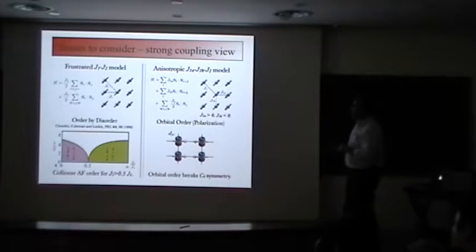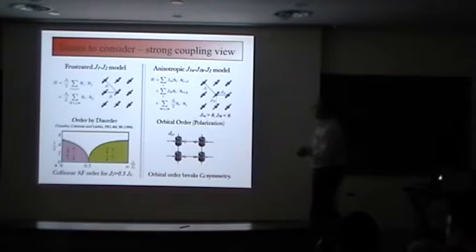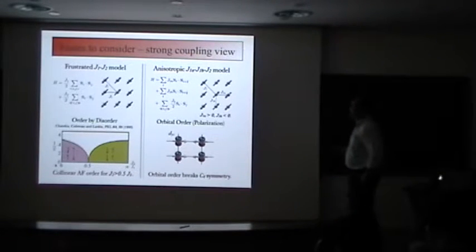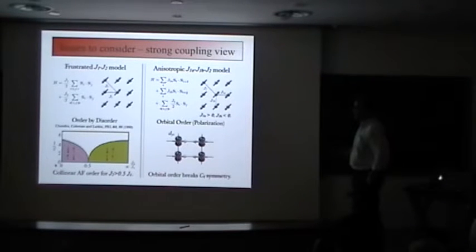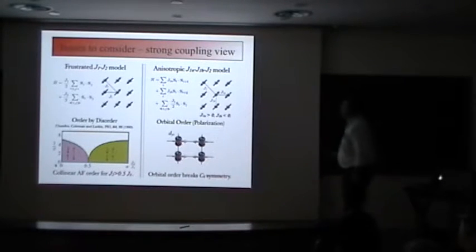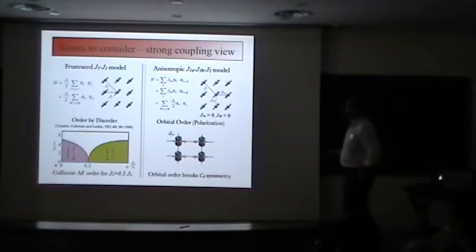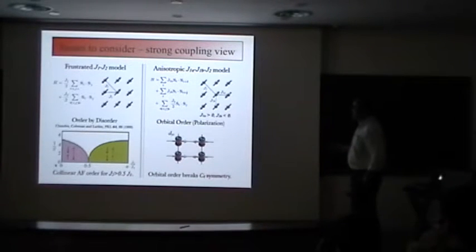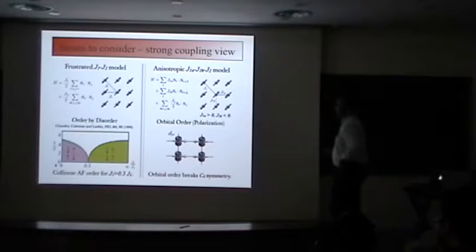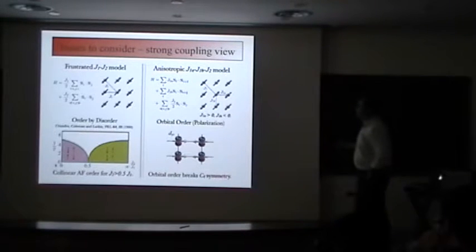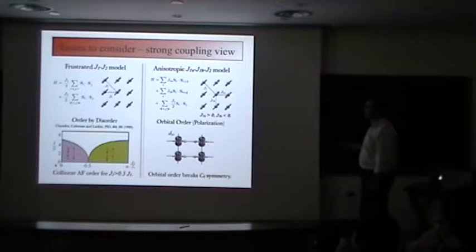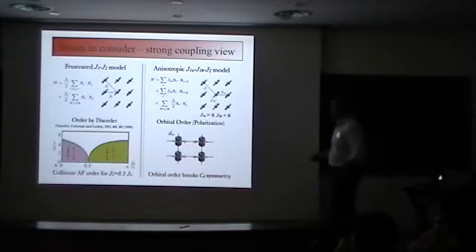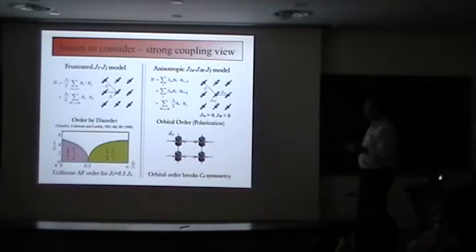So this J1, J2 model has been studied by a lot of people, looking at ways in which that could map onto the magnetism. This is a frustrated model because the system doesn't know if it wants to be this or that. Here's another particular model, again a Heisenberg-like model, but without any frustration because the magnitude of the exchanges, J1A and J1B, are taken to even be of opposite signs. So J1A, connecting nearest neighbors, could be antiferromagnetic, but J1B could be ferromagnetic, and if that happens, the system will like to align in this collinear type of fashion.